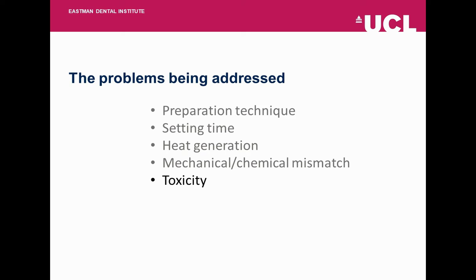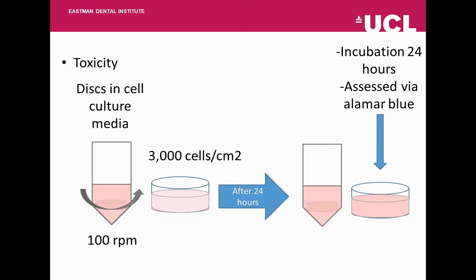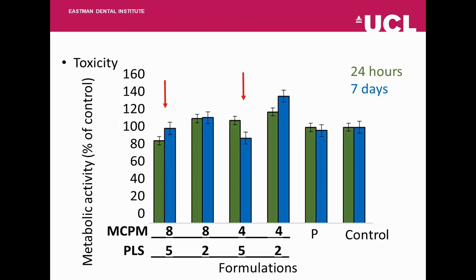To do this, I did some primary cell studies where I placed the discs in the cell culture media at 100 rotations per minute for 24 hours. At the same time, I seeded 3,000 cells per centimeter squared for 24 hours in a 96-well plate. After 24 hours, the media from the cells was removed, and the media in which the discs were submerged was added to the cells. This was then left for 24 hours and assessed via alamar blue.